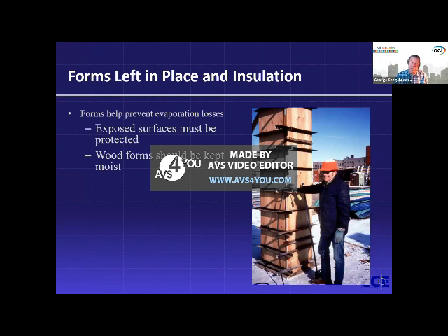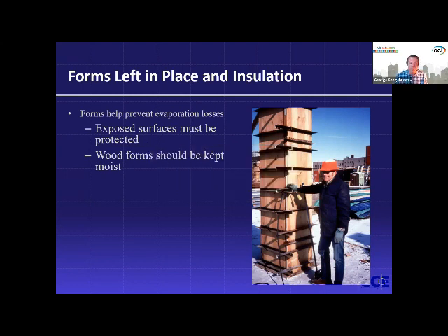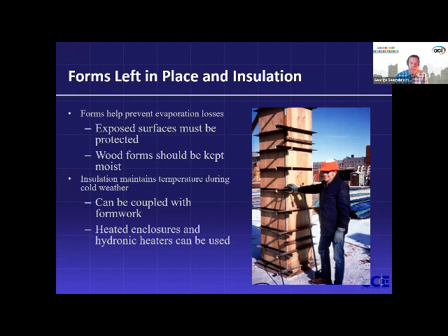If you're going to undo the forms, follow immediately with a secondary curing method. If it's not cold, you can use water, but otherwise curing compound, in order to reach the degree of maturity that you're looking for, equivalent to, let's say it's specified as a 7-day curing period. I kind of said that, coupling it with the insulation.